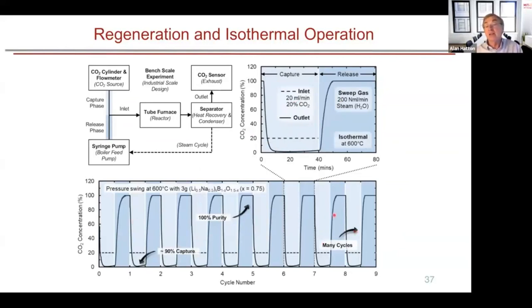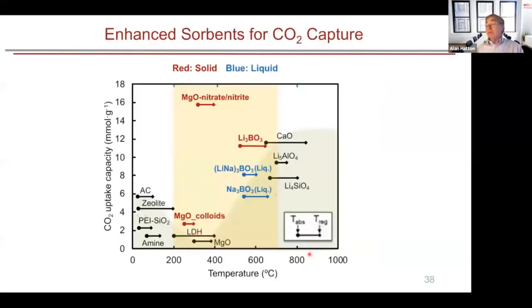And it is the purity of the release, CO2 is 100%. The capture is about 90% in these cases. And you've got many, many cycles of stable operation. So if you just want to revisit this system here, what we've got is, again, our little valley of death, you might say, in terms of the existing sorbent systems. But we have been able to fill in this gap quite successfully, looking at our magnesium oxide systems, lithium borate.